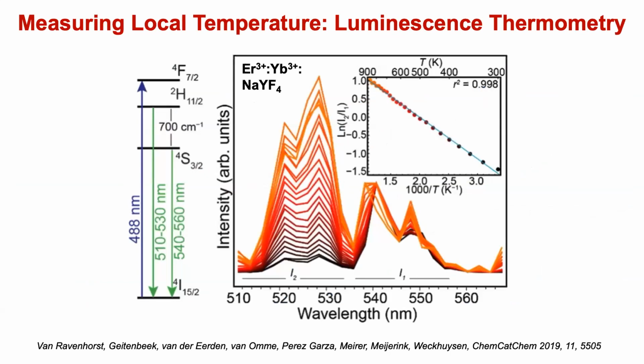We developed a method, and credits have to go to Andries Meijerink, a professor at Utrecht University who specializes in luminescence, particularly in lanthanides. You can make crystals that, when you irradiate them, go to a higher level and then fall back, the green ones. Depending on the level, they give rise to 2 bands, which I call I1 and I2 in the figure. You can make a calibration line, and from the 2 levels you can measure the temperature.